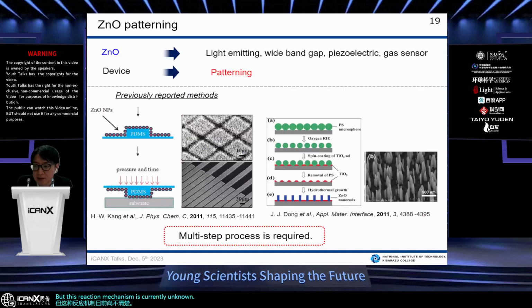Next, another demonstration of chemical reaction at the bubble is shown here. Zinc oxide is also an attractive functional material for this application. Previously, various methods have been reported for patterning, using a PDMS stamp and zinc oxide nanoparticles, and after contact and removing the mold, growing a nanowire. Another method uses polystyrene beads, removes this template, and also grows zinc oxide nanowires. These methods go through many steps. So then we tried bubble patterning.